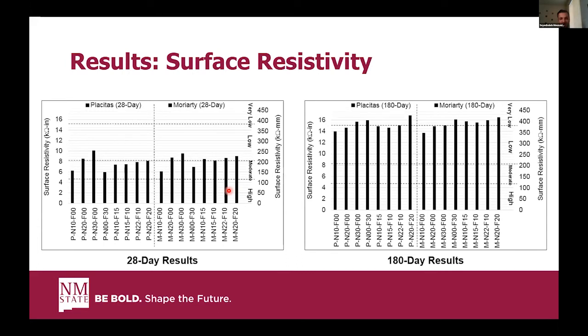Well, we have performed surface resistivity tests as well after 2 ages. The first age was 28 days, as you can see in the left figure, and we have performed after 180 days, which we call the later age. In both ages, you can see that with increasing the natural pozzolan, the surface resistivity increased, and it means that the permeability decreased for both types of aggregates.